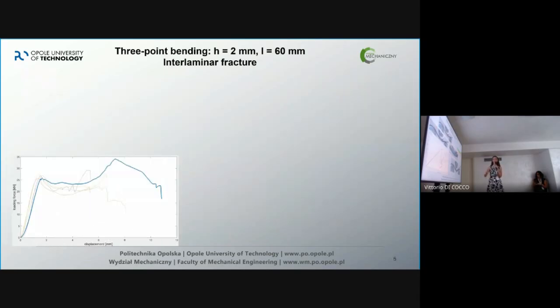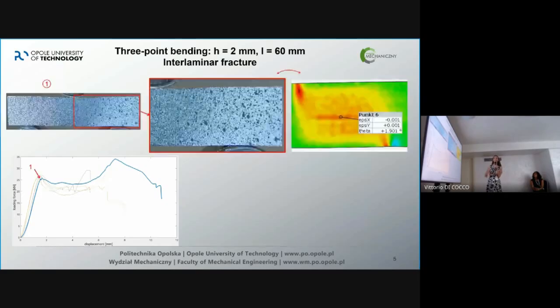Okay, another version was the three-point bending of a very thick specimen. Sorry, it should be 20 millimeters in here. So it was very thick, and I was sure that I'm going to have interlaminar failure due to shear strain. Okay. This specimen, as you can see, the epsilon X or Y are actually 0 in the location where the crack appeared in here.